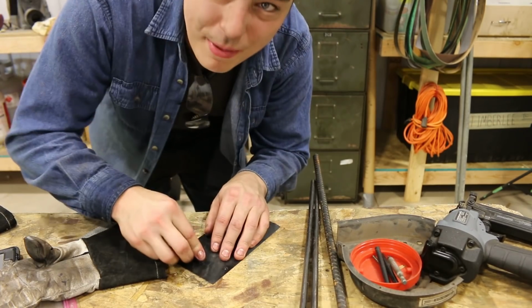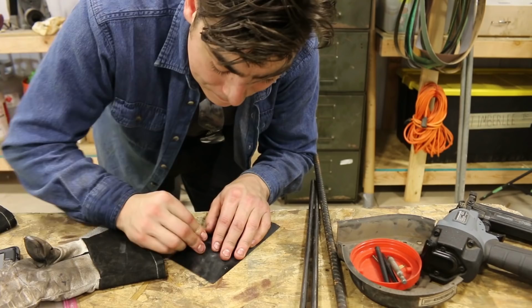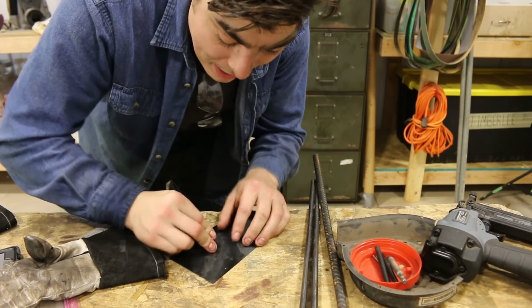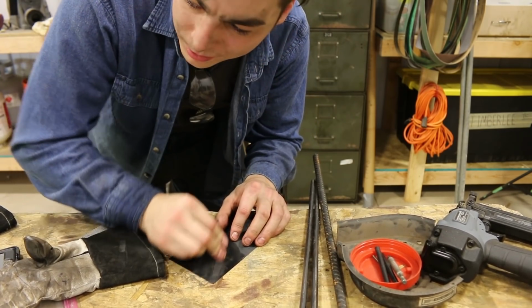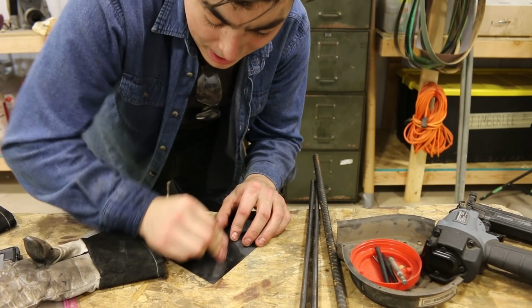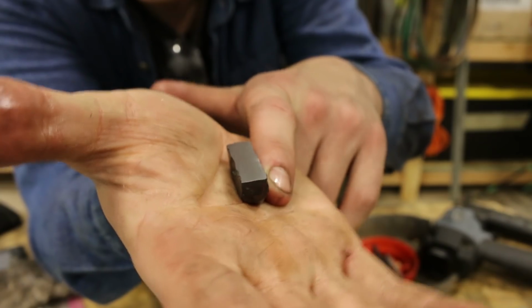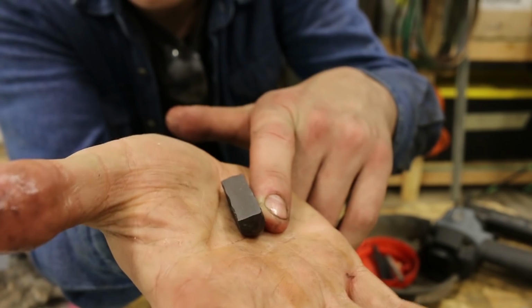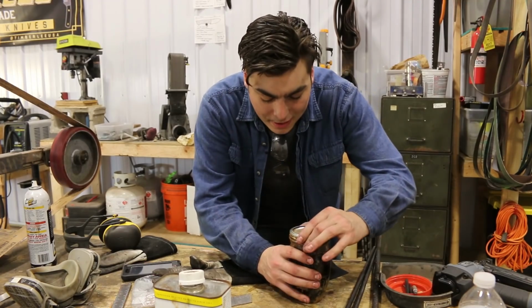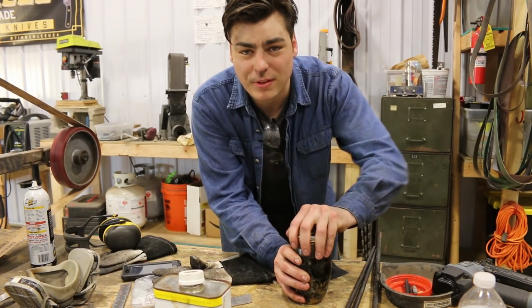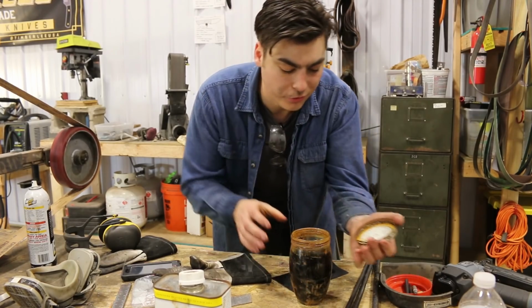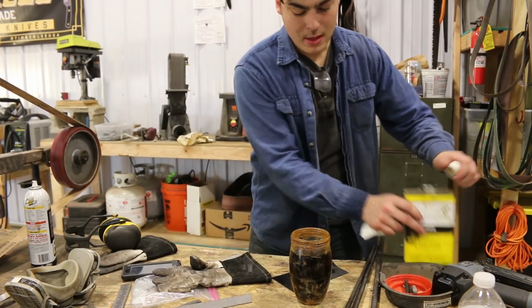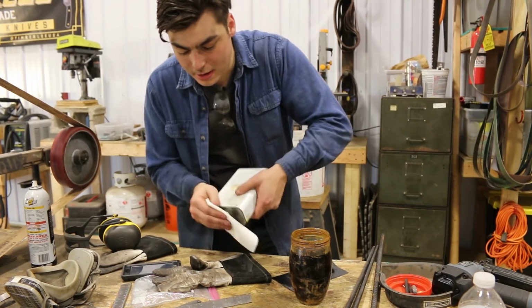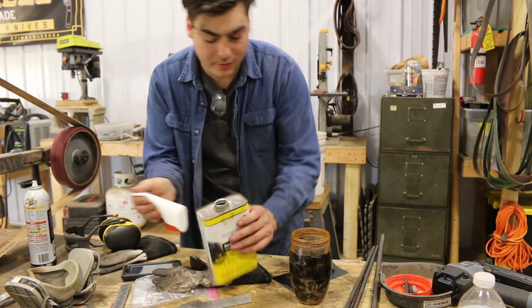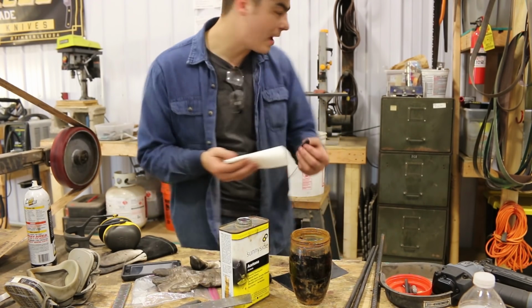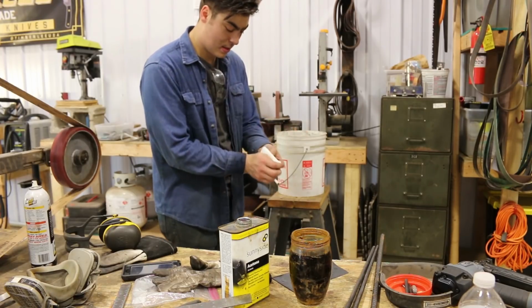And that should be plenty polished to show a pattern. A lot of times when I'm etching Damascus, I'll bring it up closer to 1500. Right now I'm just at 400, but this is just a quick little etch to reveal the layers. All right, I am using about a 50-50 ferric chloride distilled water solution. I'm gonna use some acetone just to make sure that this piece is nice and grease-free before I etch it.